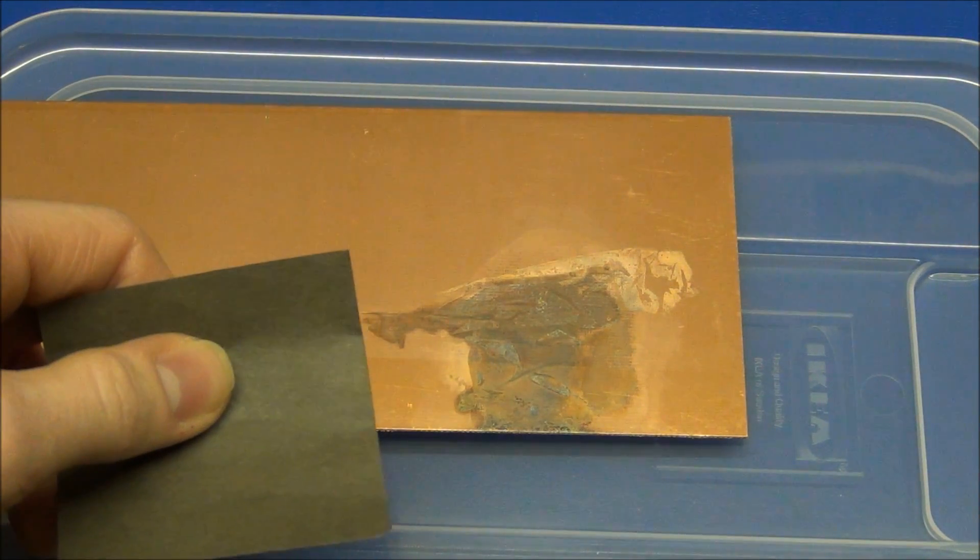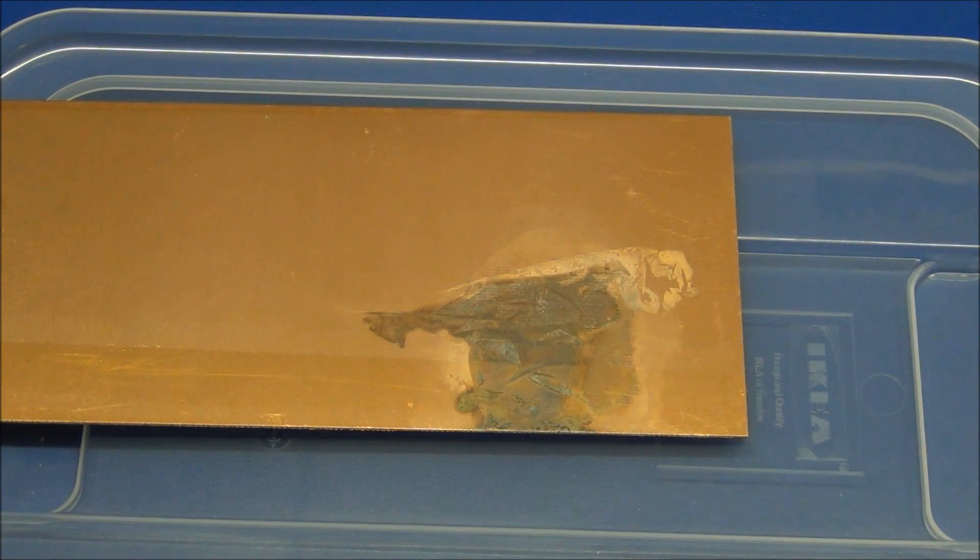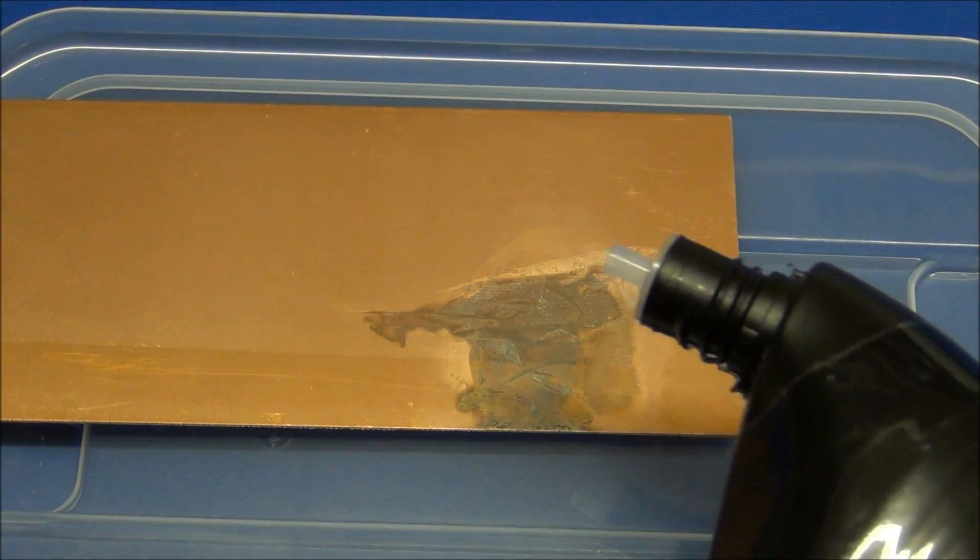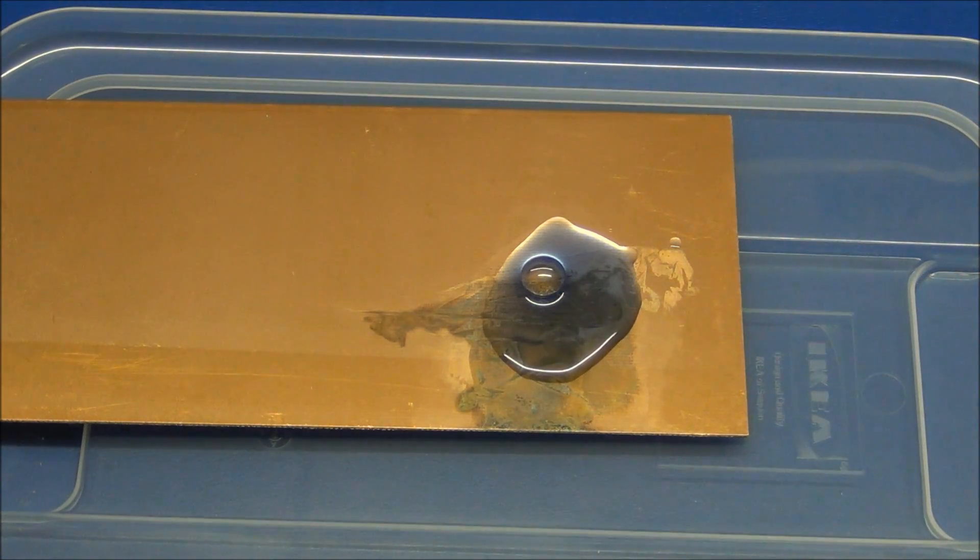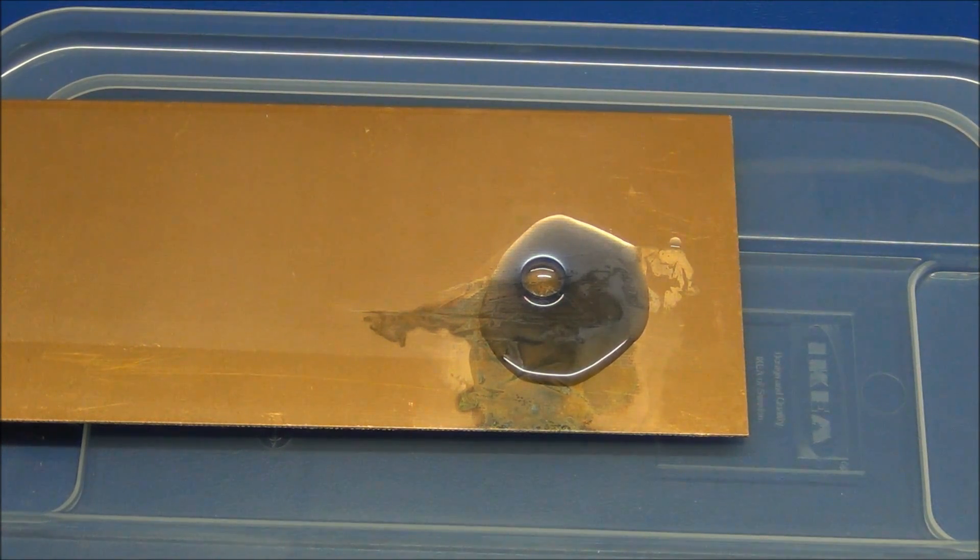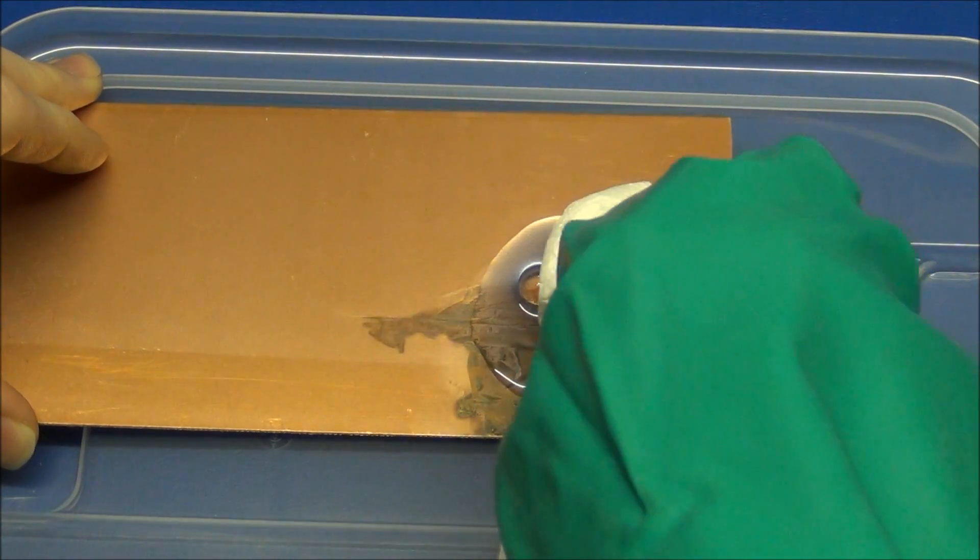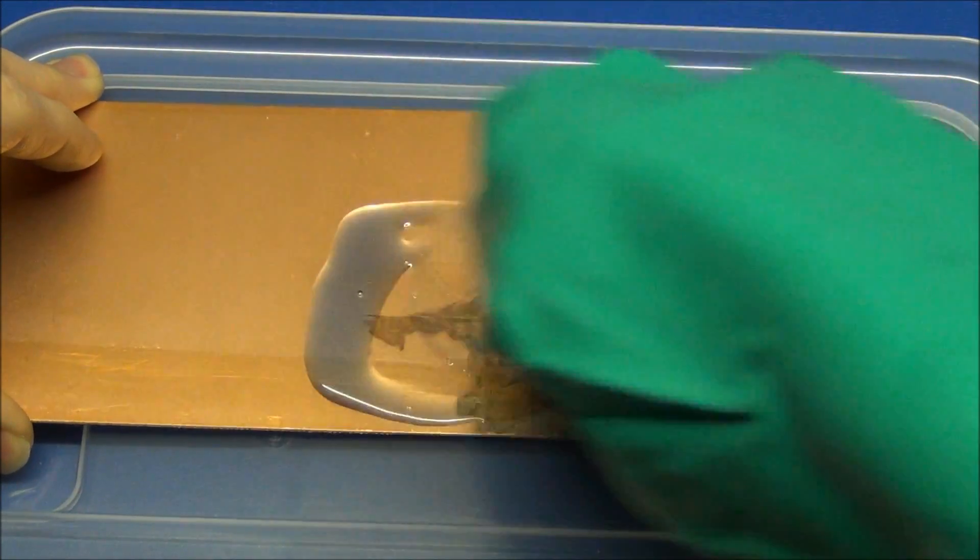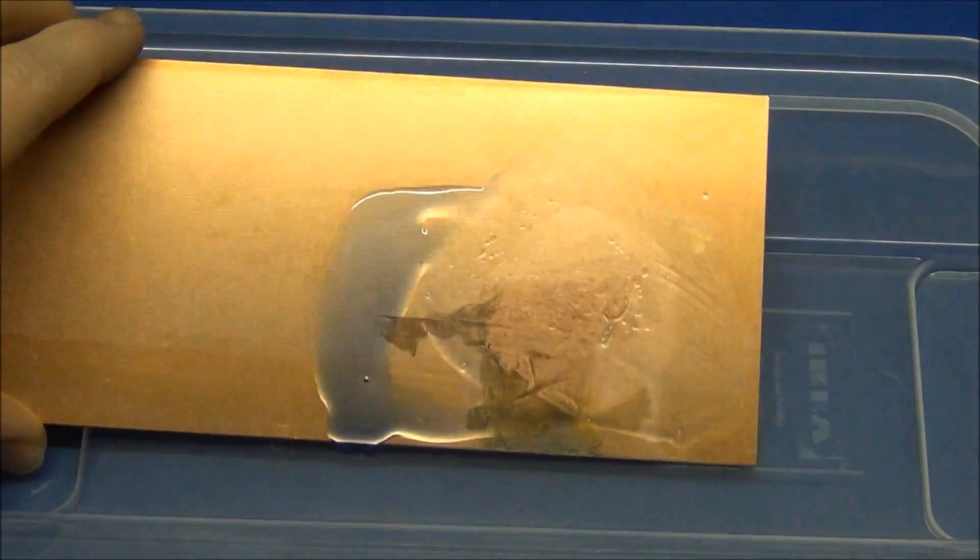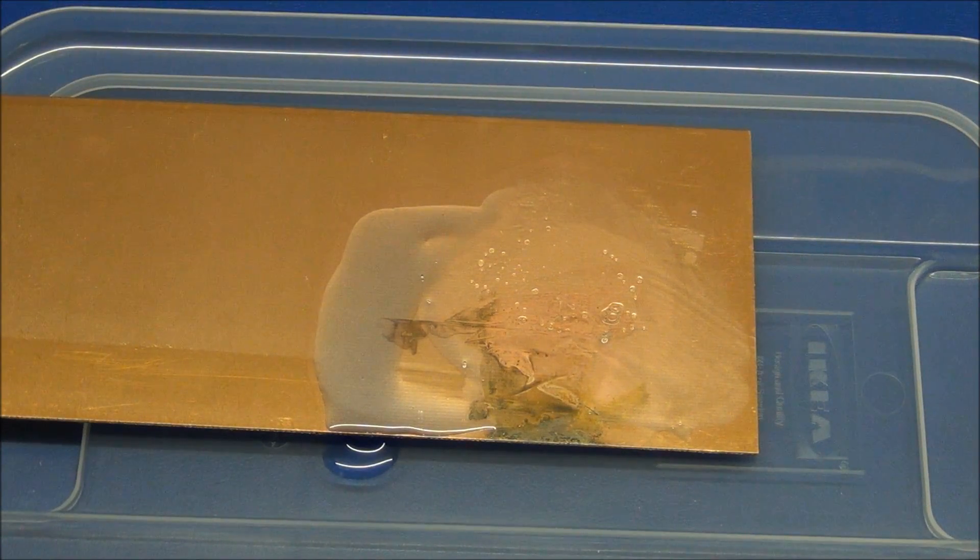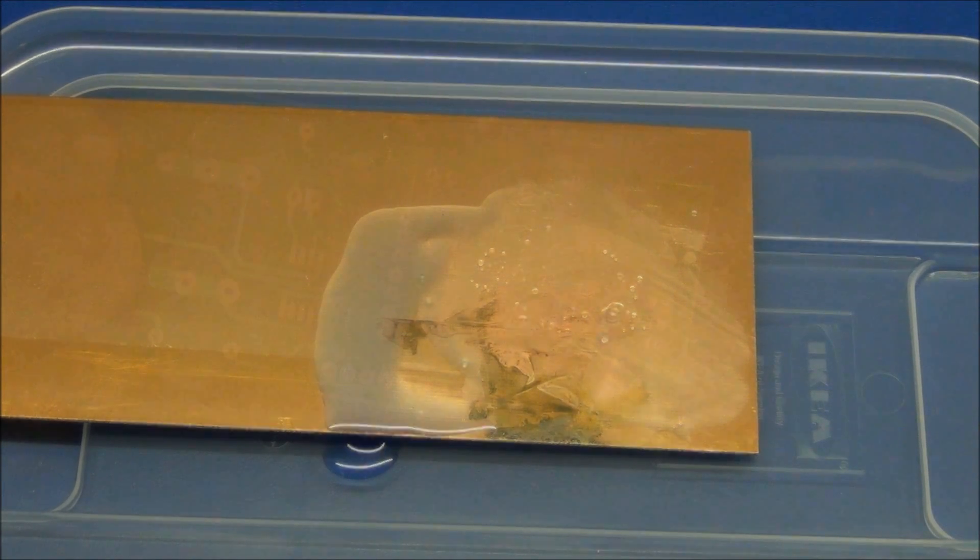In the tutorial I will be showing how to remove oxidation using sandpaper. I do recommend you use sandpaper when you are creating circuit boards. But if you want to clean an old board, you can use toilet cleaner. Add the toilet cleaner and let it work for about one minute. And after about one minute just wipe the toilet cleaner away, and it should remove oxidation from your board. But remember to clean the board with water very fast after you apply the toilet cleaner or the board will re-oxidize very quickly.